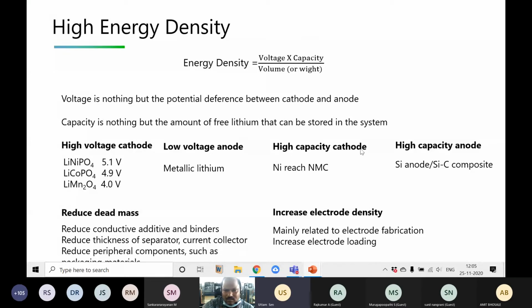In case of high capacity cathode material, we can use nickel-rich NMCs, like 811, so like 80% nickel. Currently, we are using 30% nickel, 30% manganese, 30% cobalt. From there, we have moved to 60% nickel, 20% cobalt, 20% manganese. From there, we can go even higher, 80% nickel. I'll talk about this on the next slide.